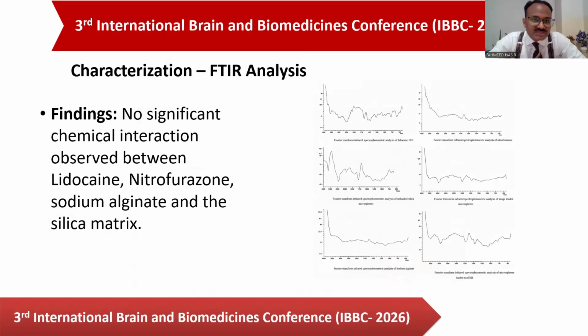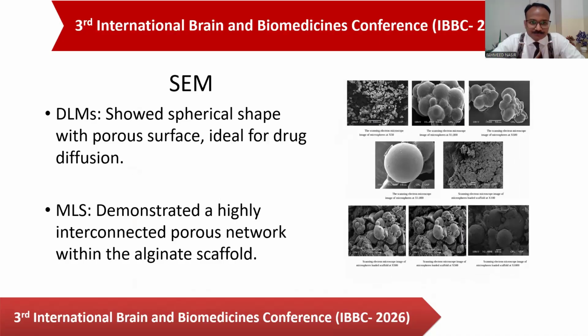If I talk about the characterization, then FTIR analysis showed there is no significant interaction between lidocaine, nitrofurazone, sodium alginate, and the silica matrix, and the peaks we can see visibly. SEM analysis showed very interestingly the round microspheres, and the microspheres-loaded scaffold demonstrated a highly interconnected porous network. And the microspheres are homogeneously suspended, very well suspended in the scaffold.